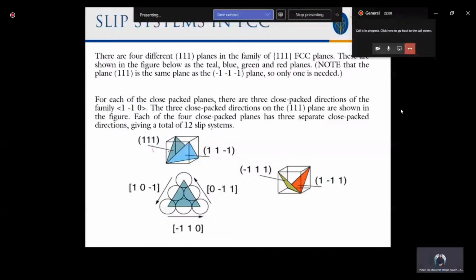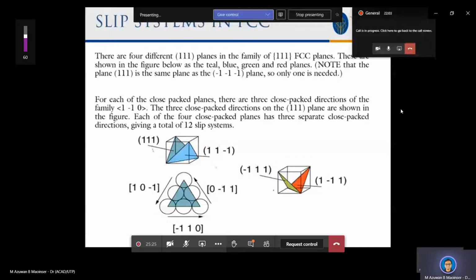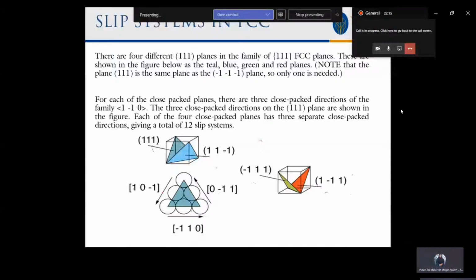The (111), (11-1), (-111) and (1-11) planes are all the family of {111} planes. And the direction is in terms of <110>, so it can be negative in X, negative in Y, and negative in Z. So you get three variations. Every plane will have three directions, so four planes times three directions, you get 12. This is how you get 12 slip systems for FCC.